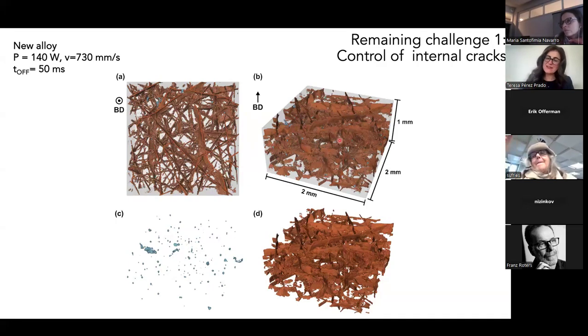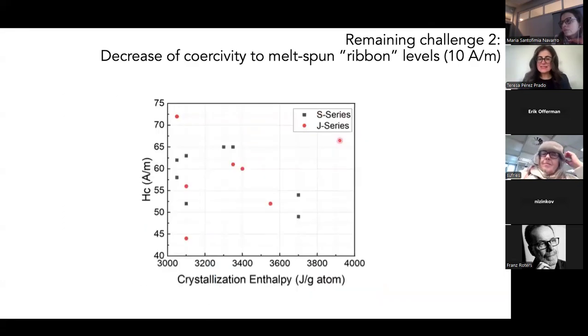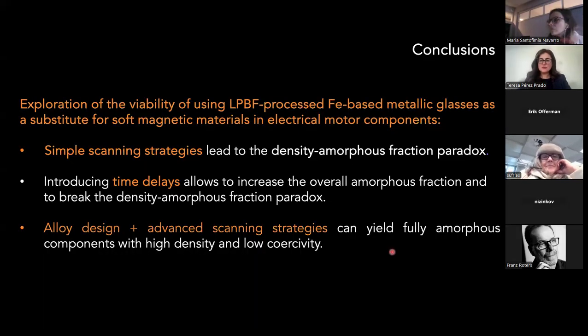Cracks are not necessarily bad because they can also act as insulating agents. But of course, this is if we can control the appearance of cracks. And then the second remaining challenge is to reduce this coercive field to get really to the value of the Metglas ribbon. For that, there are also some colleagues in the project already carrying out heat treatments to reduce the internal stress levels, with very promising results, which I guess will be published soon. And with that, I want to thank you all very much.